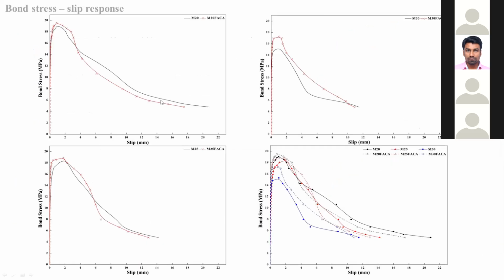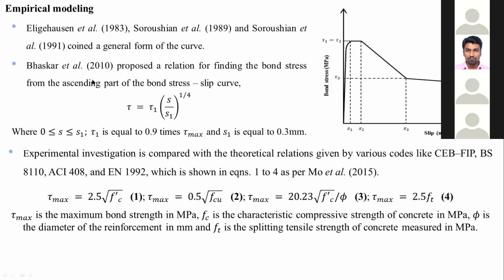Now these are the curves which I found, and I also found the empirical modeling of the bond stress versus slip curve, which was examined by Eligehausen, Popov and Bertero in 89 and also 91, and they also found the empirical equation. Bhaskar et al. validate that this experiment comes in line with the above authors' research outcomes, and my research also comes in line with Bhaskar et al. 2010. This is the generalized equation for the empirical modeling.